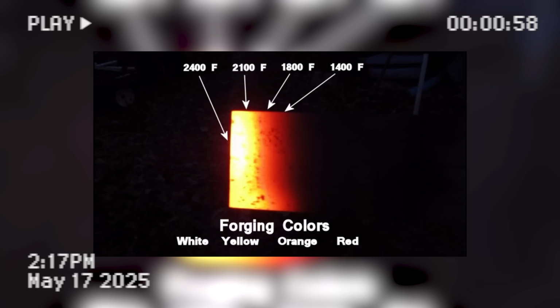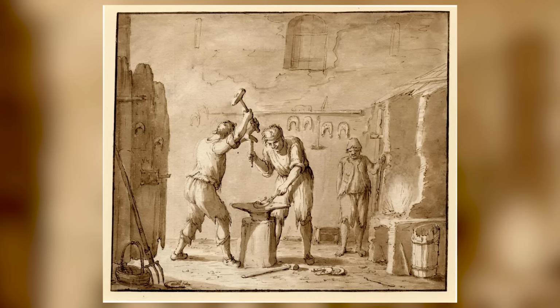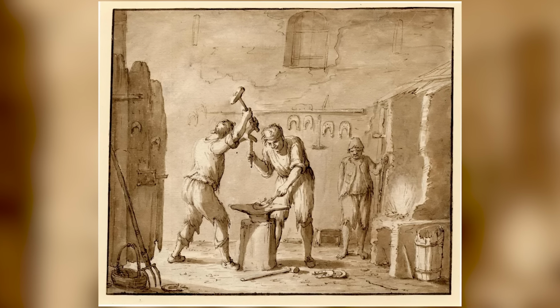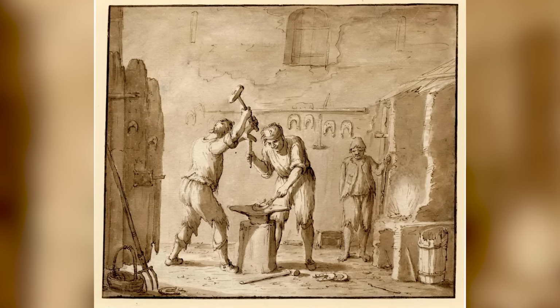Yellow was 1200 degrees Celsius, the danger zone. The iron becomes almost spongy. Only masters worked at this temperature. One mistake and slag pockets open inside the metal, ruining hours of work. White was 1300 degrees Celsius, the burning point. At this temperature, iron begins to combust, oxidizing rapidly in the air. The work is destroyed. Historical records and modern experiments demonstrate what happens when this temperature discipline is ignored.